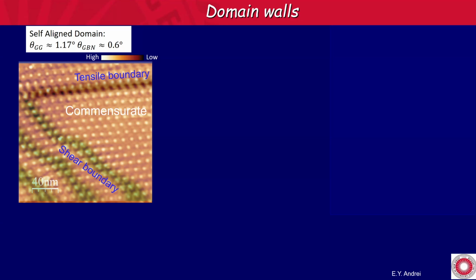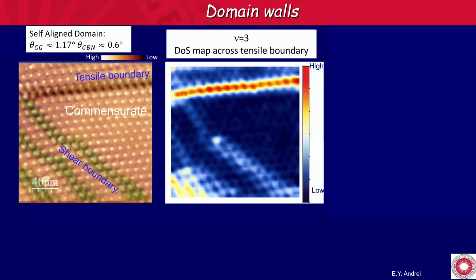And here we have a shear boundary. But in here we have a 1-to-1 commensurate crystal. And if you look inside, if you do density of states maps as a function of the filling of 3, this is the filling where the transport people saw the quantum anomalous Hall effect, you see that one row below this missing row here. So inside the commensurate region, you have something that looks like an edge state.